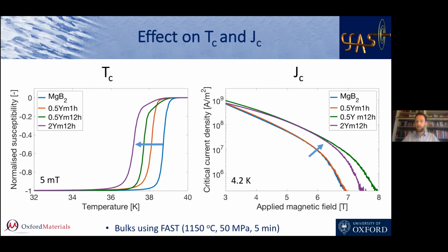What was interesting is that if we only ball mill an hour, we didn't have any improvement. And that can be correlated to the microstructure, which essentially showed that for low milling time, we didn't have a small dispersion, but rather big agglomerates, which meant that we didn't mix it well enough and for long enough to have the positive effect of the new pinning sites.